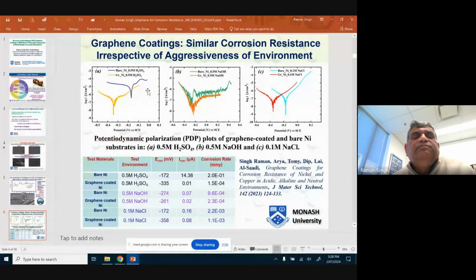Whereas if you have bare nickel, it corrodes at a different rate depending on the aggressiveness of the environment. Like in sulfuric acid, it corrodes at a much higher rate. You can see that the corrosion rate is much higher. The higher the value, and it's a log plot by the way, the higher the value of this intercept, the greater is the corrosion rate. So graphene coated nickel gives the same degree of corrosion resistance irrespective of the type of environment, whereas the bare nickel corrodes at different rates depending on the aggressiveness of the environment.